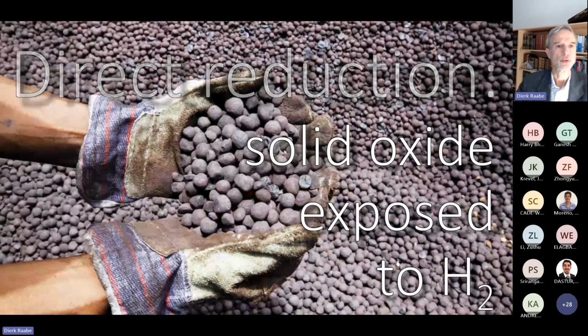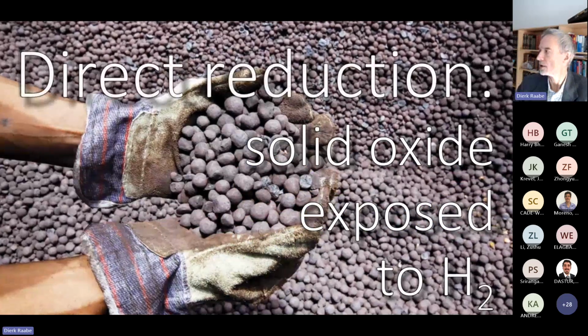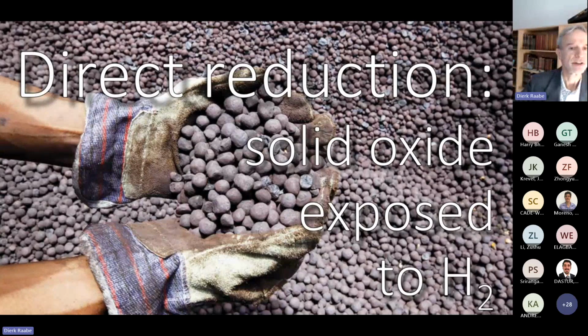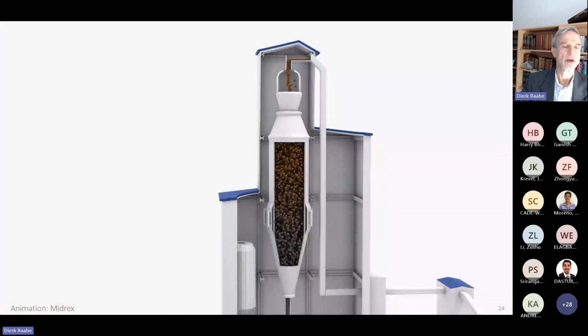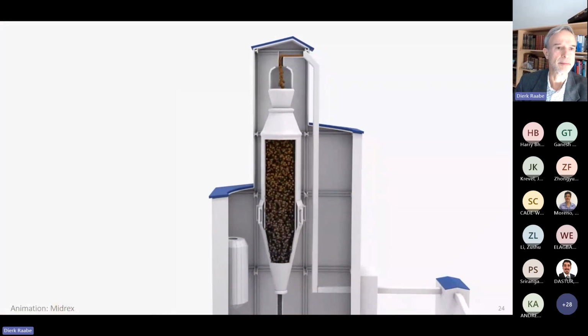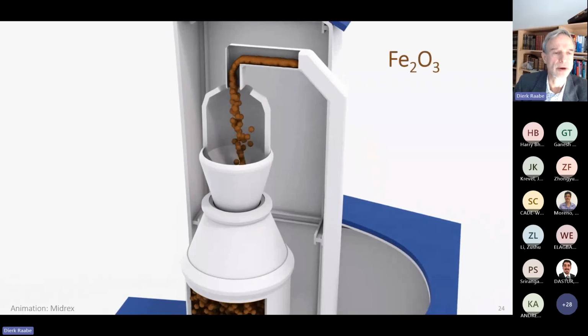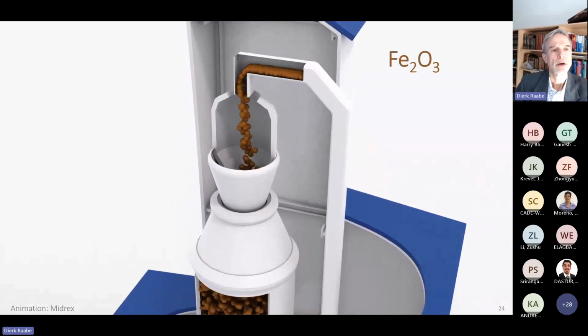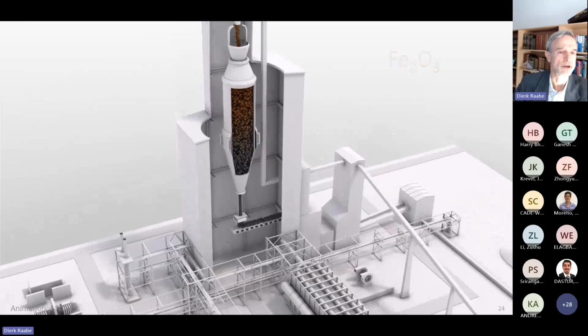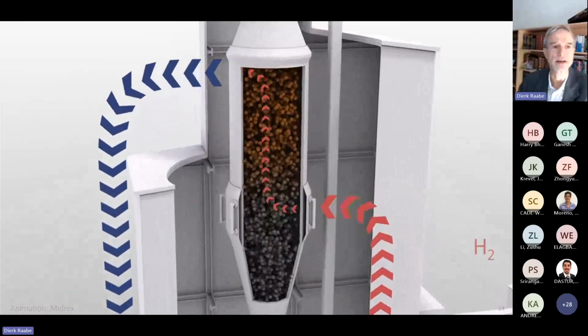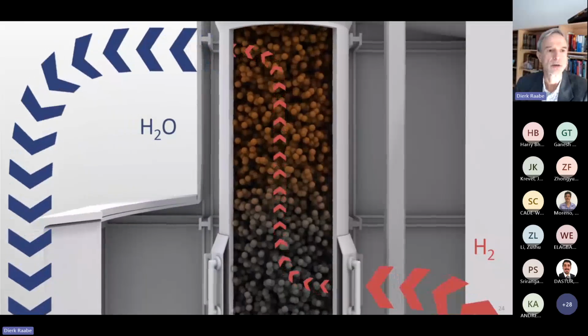Now let me say a few words about direct reduction, because it has probably today the highest TRL level, as you all know. And we do experiments like several other groups also, where we expose solid oxides. These are classical sintered pellets with a diameter of a little bit more than a centimeter exposed to hydrogen or hydrogen-containing gases. And that was usually done here, like in this animation from the company Midrex. They built these reactors from reforming methane. And the mixed reform gas, which also contained hydrogen, was classically used in these reactors, which, however, had only a small market share below 5%.